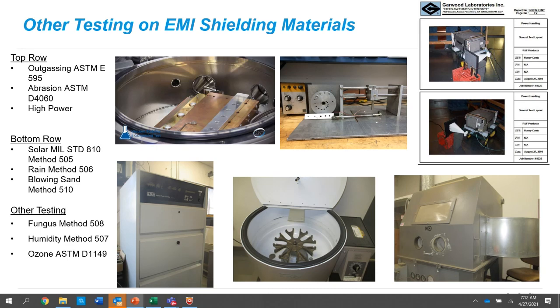So what this test was basically a 15 gigahertz antenna cranked up to very high power, and we were trying to generate anywhere from 1 to 5 watts per square inch onto this honeycomb panel. It was an interesting test in the fact that we tested open-celled foam, which actually tested better than the honeycomb. The honeycomb was mounted on a conductive ground plane, so there was a backing to it.